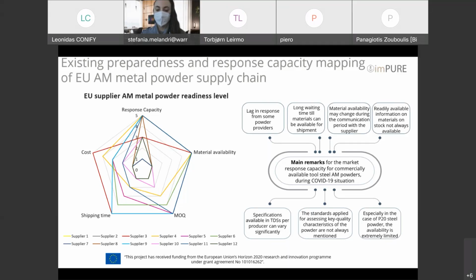And there's limited readily available information on materials on stock. The specifications, according to the technical data sheets per producer, can vary significantly, even for the same alloy, for example, the same tool steel. And the standards applied for assessing key quality characteristics of the powders are not always mentioned, which is an important factor when you want quality parts and need your feedstock material to be of certain standards. Especially in the case of P20 steel, powder availability was extremely limited. We did that based on different suppliers for different tool steel and maraging steels. So next slide, please.